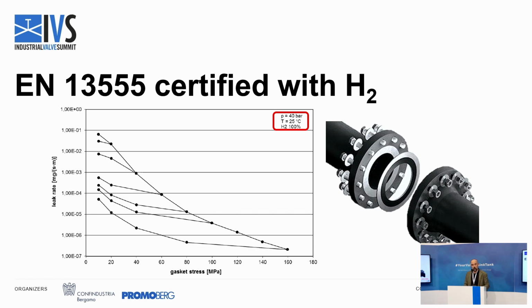And we discovered that actually we can make a good comparison between helium and hydrogen in these kind of conditions with static condition. And if we create the graph based on the 13555, this graph is basically very similar, and it's basically the same as the same test with helium, with the same condition, pressure and temperature. So there's something with the mobility of hydrogen that need to be tested and need to be checked, because the sealing test on a valve could be not enough. We need to test the materials in another way, and not just with a pressurization test on a valve.